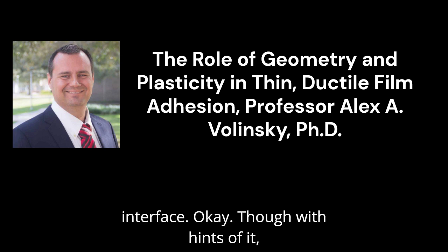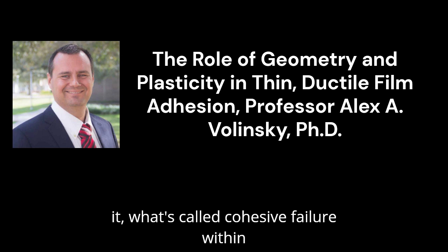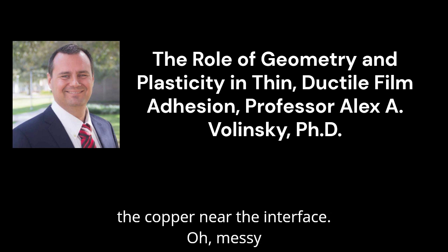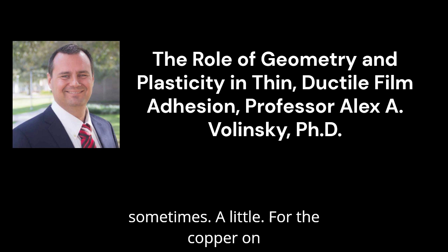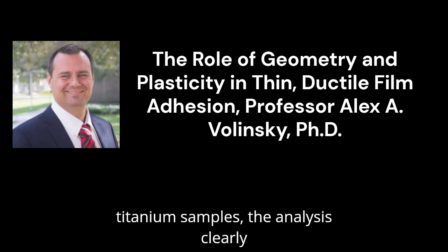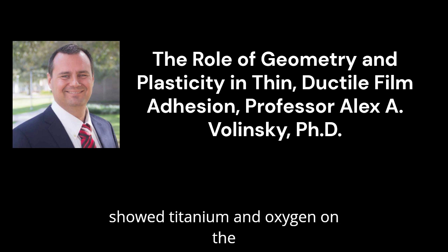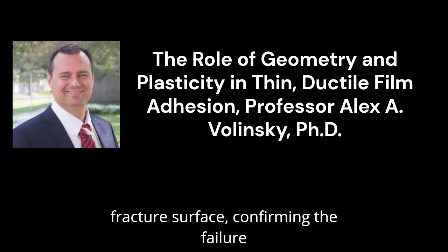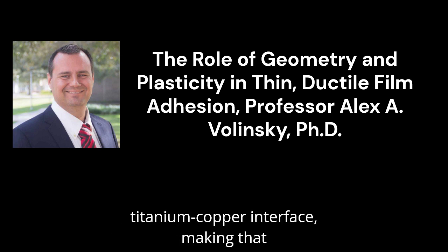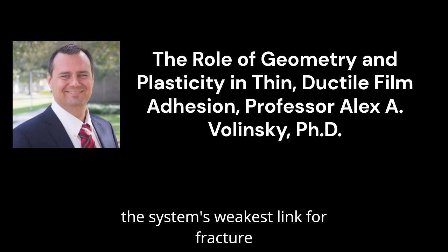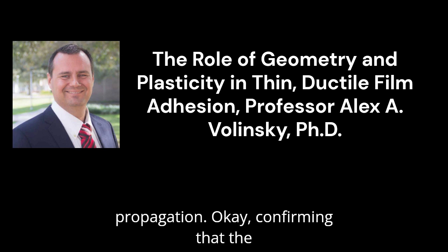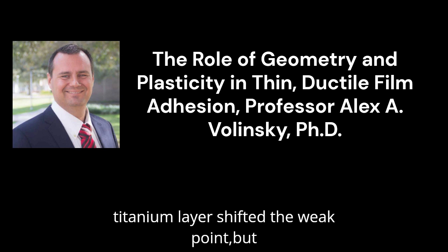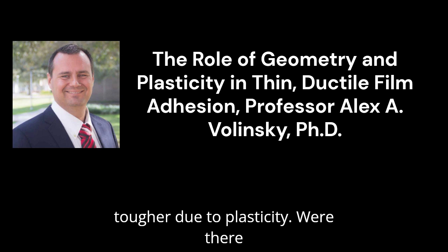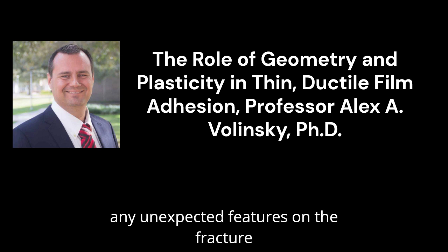Okay. Though, with hints of it sometimes pulling a bit of copper with it, what's called cohesive failure within the copper near the interface. A little messy sometimes. A little. For the copper on titanium samples, the analysis clearly showed titanium and oxygen on the fracture surface, confirming the failure consistently occurred along the titanium-copper interface, making that the system's weakest link for fracture propagation. Okay, confirming that the titanium layer shifted the weak point, but in a way that made the overall system tougher due to plasticity. Were there any unexpected features on the fracture surfaces?